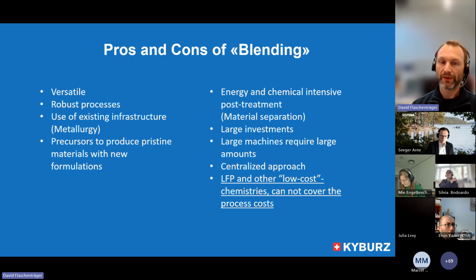And that becomes a real big problem if we are talking about low-cost chemistries, such as LFP, but also sodium ion and what's around the corner, because the main driver for these chemistries is basically the low price point, and the low price point comes from cheap materials. And if the materials are cheap, you cannot afford expensive processes to gain cheap materials. The economics simply won't work. From a technical point of view, there's absolutely nothing wrong with putting an LFP battery into a hydro process. But every accountant is going to tell you that it's not going to pay off. And that's the main issue here with these low-cost chemistries.